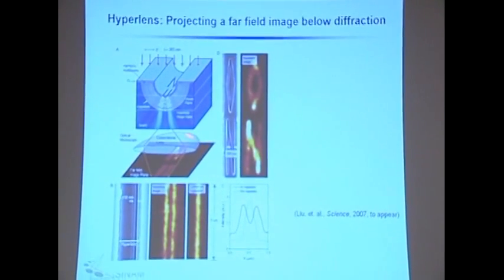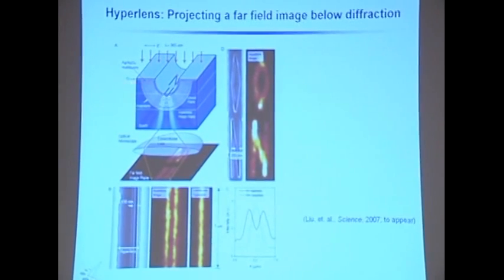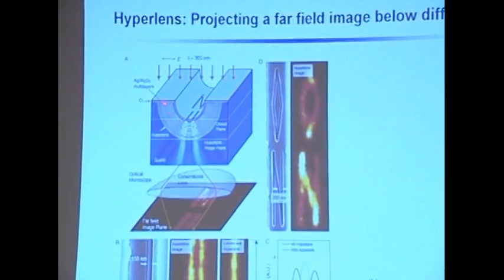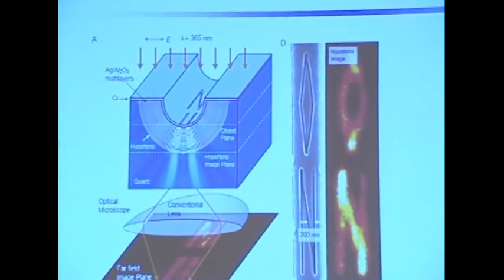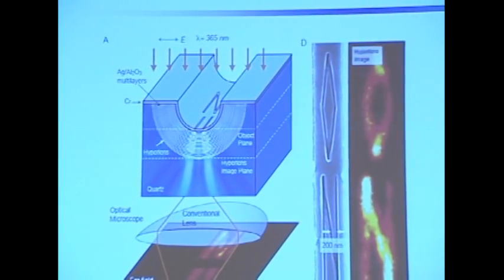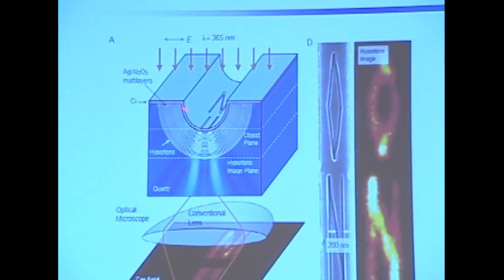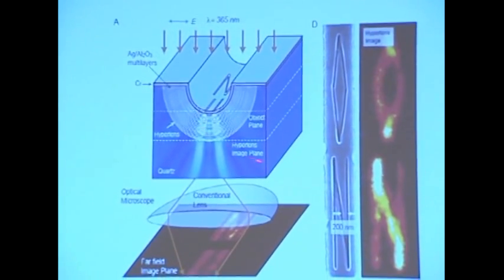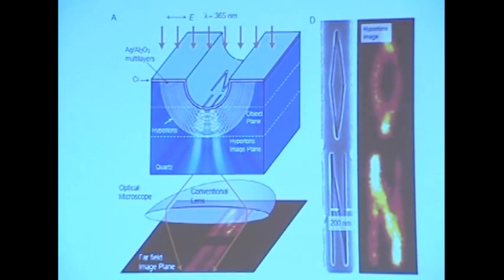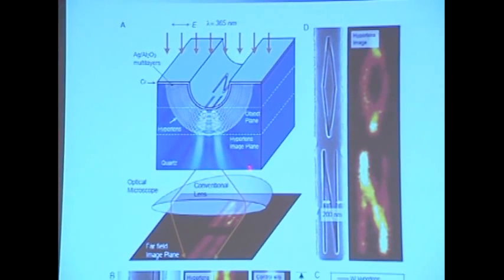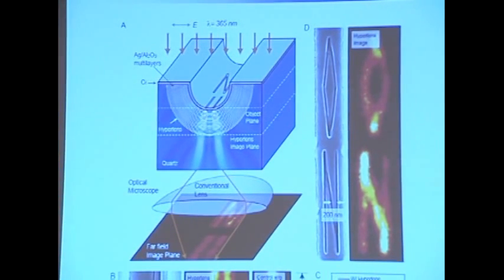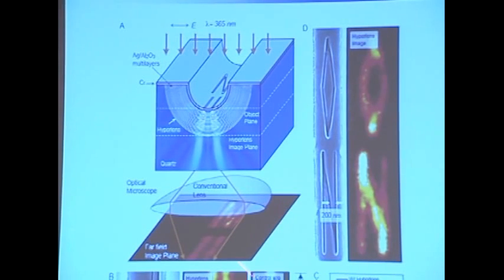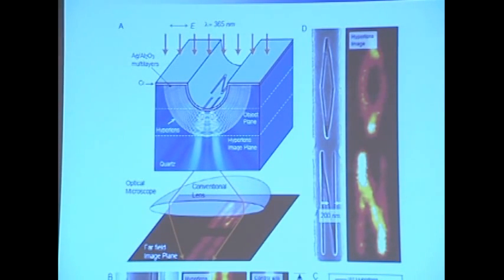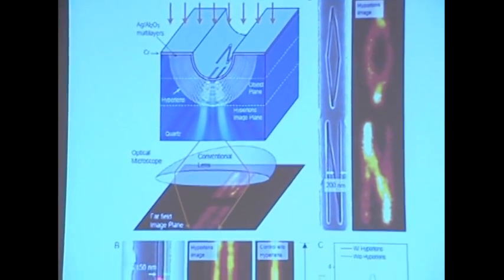So this is the experiment we recently did. We fabricated this structure with a cylindrical geometry, with multi-layers of silver and aluminum oxide, each about 30 nanometers. And indeed, you can make this very high K-vector wave propagate and eventually become propagating in the vacuum or a positive medium, in this case glass or air. This is the first experiment, demonstrating about 150 nanometers.